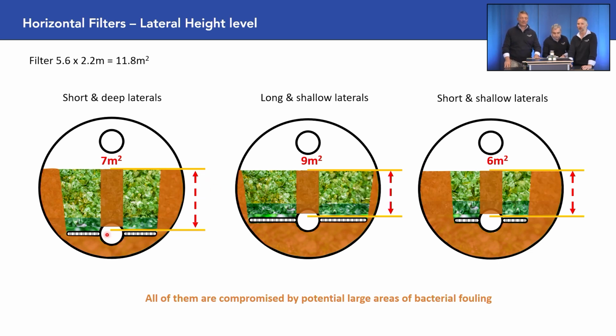So some try to get as low as possible to achieve as much media bed depth as possible, and that's a good thing. However, just purely because of the roundness of your horizontal filter, that really compromises the length of your lateral, and therefore you have very big dead areas both on the sides and in the middle, as we said earlier on, above the big pipe. So going from a 11.8 square meter filter, you can often end up with only 7 square meters. If you bring that lateral higher up, you have an even bigger dead area below the laterals. You have a shorter bed depth, so compromising filtration performance of the fines, as we showed you earlier on. But then your laterals are also a lot longer, which we've shown previously also don't work as well.